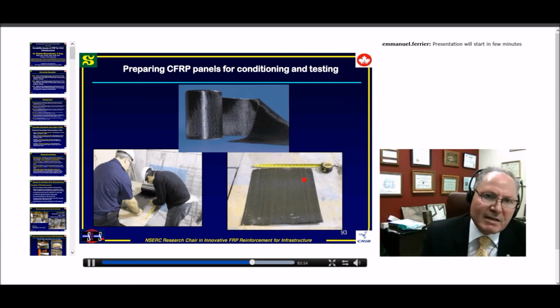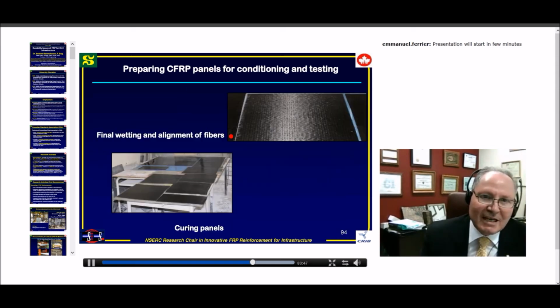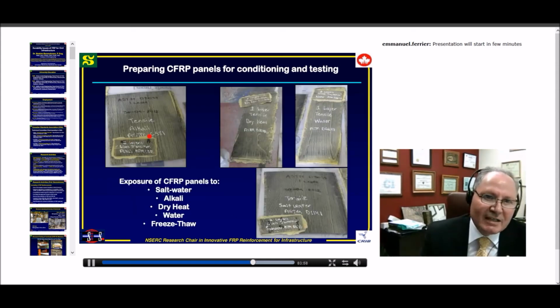Yeah, this is showing some preparation of the specimen. My colleague Emmanuel knows more than me in this field, so this is showing the FRP, the carbon sheet, and this is preparing the panels, as you can see here in the lab. We did different layers, 1 layer, 2 layers, 3 layers, and so on. This is all the panels prepared for exposure in salt water, alkali, dry heat, water, freeze-thaw.